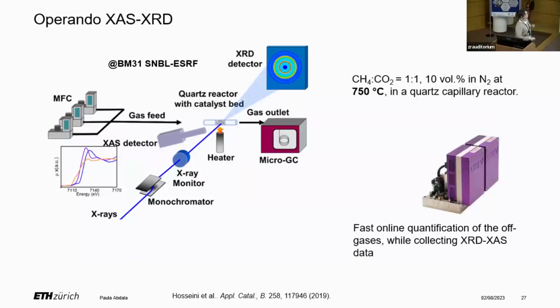In this case, we follow the reaction again. This is very important for us to correlate the solid state reaction with the gas phase reaction. And in this case, we use micro GC, which is faster than the FID one, and we are at a time resolution of below 1 minute.